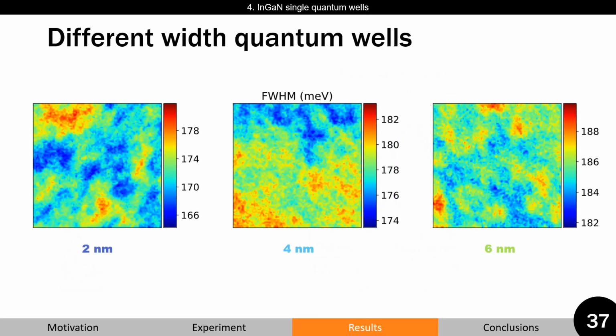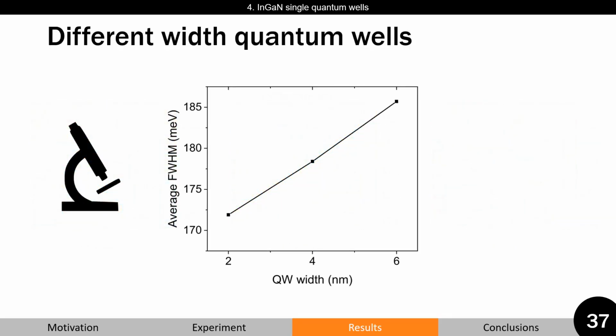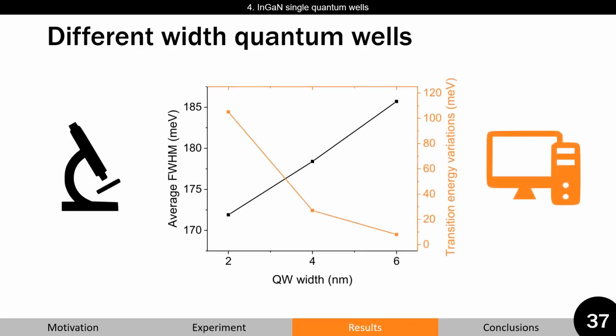These are the full-width half-maximum SNOM maps. One can observe from color bars that full-width line width variation increases with quantum well thickness. By plotting the average line width versus quantum well width, we observe a positive trend. Now, our simulations show that the biggest quantum well width variations would have the largest effect for the narrowest quantum well. In other words, if quantum well width variations were the dominant mechanism, one would expect the largest line width for the narrowest quantum well. Thus, photoluminescence broadening in these structures is mostly determined by composition variations.